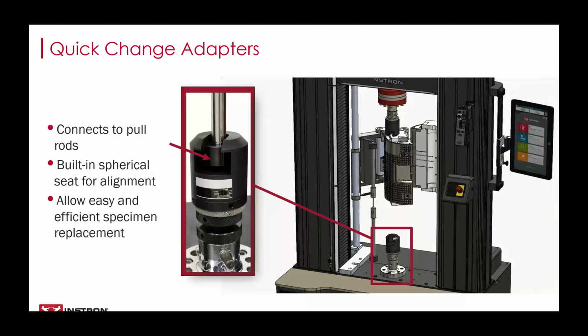Once the load string's in place, you can see the crosshead move up slightly. This is a small preload that is being applied to remove any slack that might be in your load string. You may ask, is the preload necessary? And yes, we always recommend it. The reason being is as a specimen heats up, it will soften. So this might create slack in the load string, and that presents an opportunity for misalignment. So having a preload just ensures that that washer is gonna stay fixed in the holder and won't slide around.